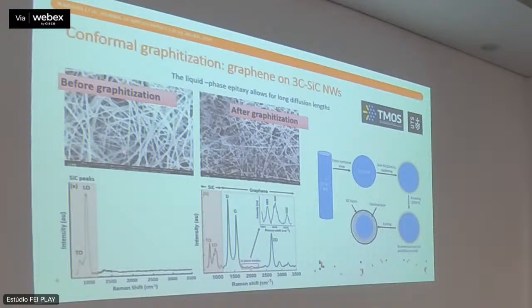These are silicon carbide wires grown on top of silicon wafers that were made by some collaborators in Italy. And we wanted to see whether this process, putting down these blanket layers of copper and nickel, would also catalyze the growth of graphene around these very small nanowires. The diameter is about 50 nanometers on average. It turns out that that's the case. You see, initially there is no graphene, and then we obtain the actual wires coated by graphene.